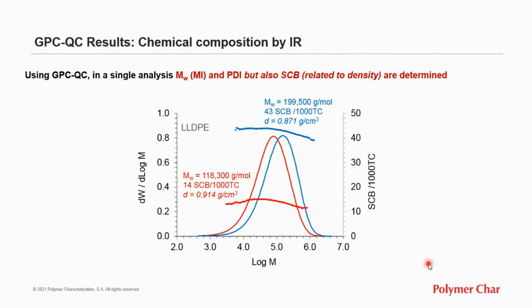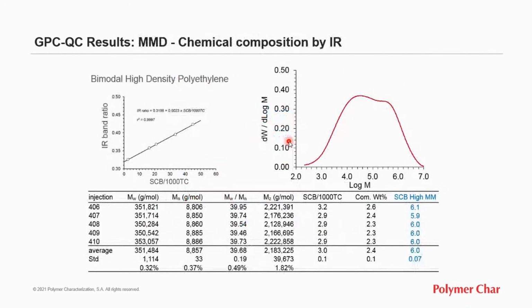As an application, we see here 2 copolymers with their molar mass distributions, and also the short chain branching thanks to the IR detector. So from the molar mass and the IR detected short chain branching, it is possible to estimate melt index and density as well, if that is necessary.